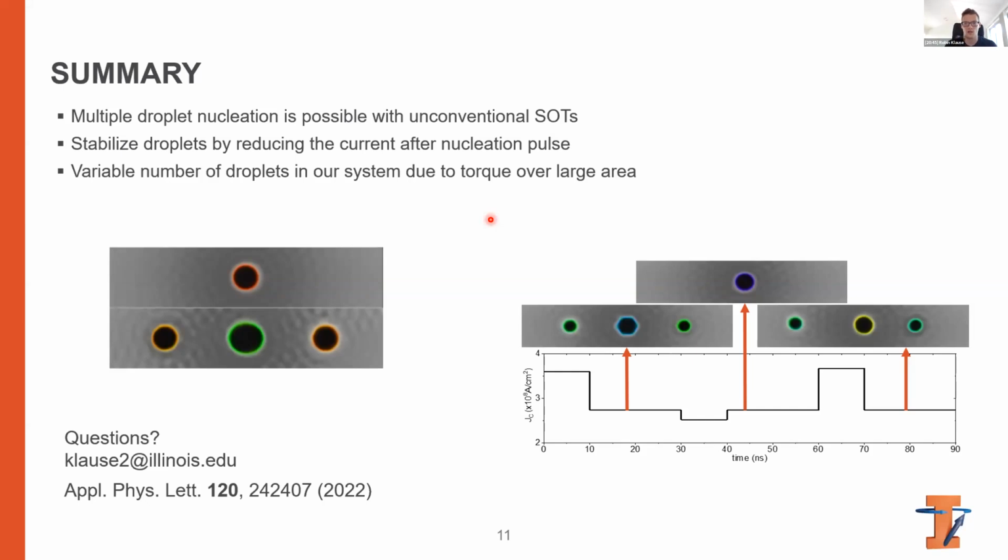And then the other thing is how far above the necessary nucleation current you are. So if you apply a higher current than necessary, you will also generate more droplets more quickly, and then they will expand more quickly and things become chaotic more quickly.